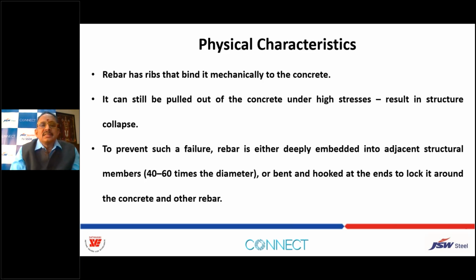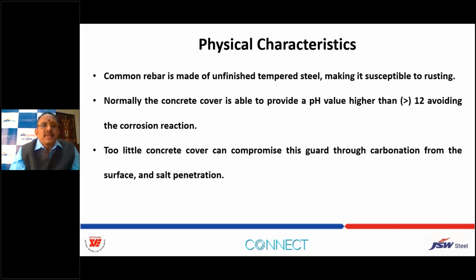So rebar has ribs that bind it mechanically to the concrete. The ribs, that mechanical bond resistance it will develop. It's not only by the chemical bond stress, and it can still be pulled out of concrete under high stresses. And so to prevent such failure, it should be embedded with enough concrete and anchorage to be provided to the reinforcement. And common rebar is made of unfinished tempered steel, making it susceptible to rusting.